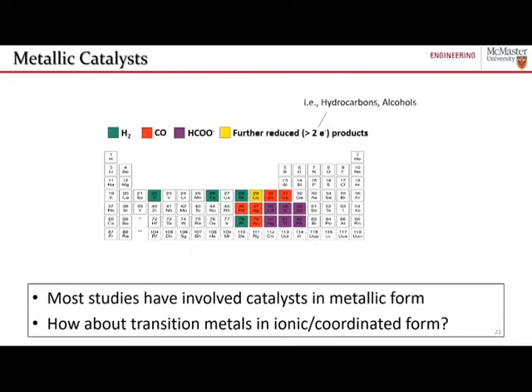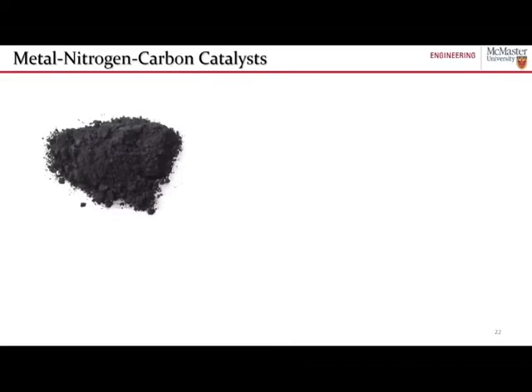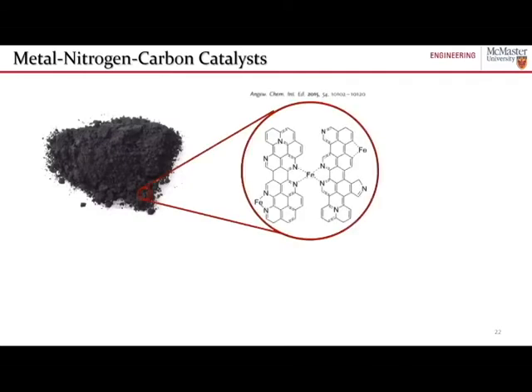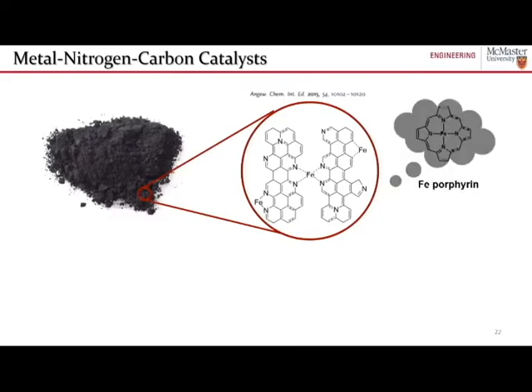So particularly, I'm going to talk about a class of catalysts that we refer to as metal nitrogen carbon catalysts. So to the eye, it just looks like a bunch of black powder, black carbonaceous powder. But on the atomic level, it has these individual metal ion sites coordinated with nitrogen dopants, all embedded within this graphitic carbon matrix. Interestingly, the active sites that are hypothesized in these catalyst materials are these metal centers that have similar structures that are analogous to something like an iron porphyrin or a metal porphyrin structure.